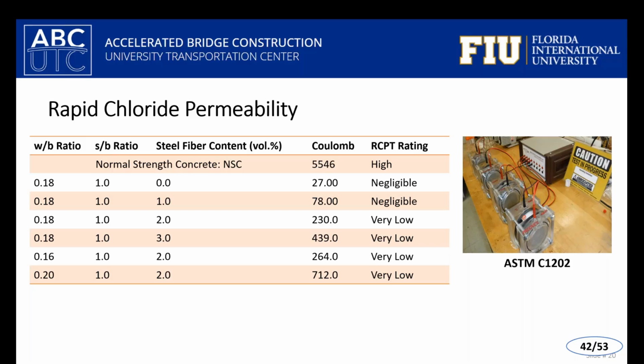Here are some results for the rapid chloride permeability test with migration test, looking at some of the UHPC mixes that are being developed and used here at FIU. And typically, the first row will be for normal strength concrete. A very high amount of Coulomb charge passes through the system, so the rating is high. Evidently, ions can pass through this electric field very quickly. And compared to that, for our UHPC material, the amount of Coulomb charge passed is much smaller, in some cases considered negligible or very low, verifying again that UHPC is a very dense material and allows for slow penetration of aggressive ionic species that can cause corrosion to occur.